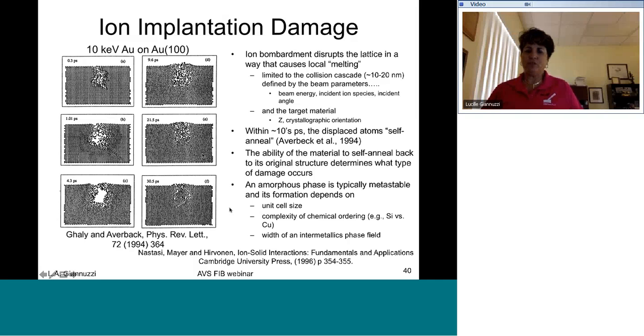So in general, the amorphous phase will be metastable, and its formation depends on the unit cell size, the complexity of chemical ordering, or the width of the intermetallic phase field. So the more complex this sample surface is, the more likely it is that it will form an amorphous phase. So, for example, gold and your simple FCC, BCC metals, and even some HCP metals will tend not to form an amorphous layer, but silicon forms an amorphous layer because it's a more complex covalently bonded material.